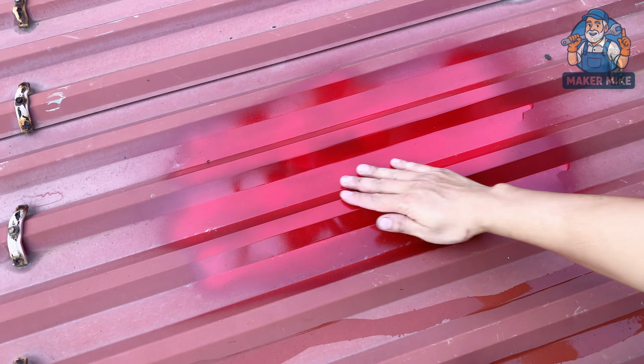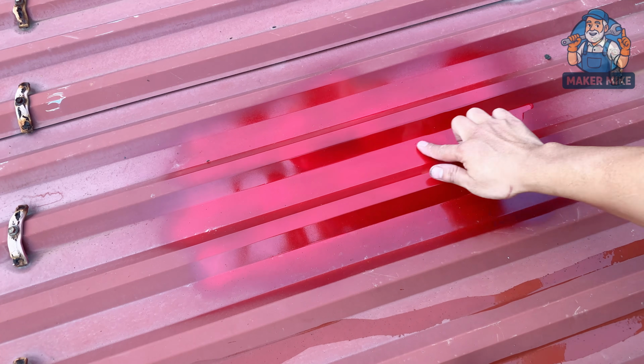Finally, the metal roof sheet surface. After drying, the coating sticks relatively firmly, and the surface has fairly good water resistance in this test. For a DIY test at home, this mixture shows a pretty interesting ability to coat, resist water, and bond.